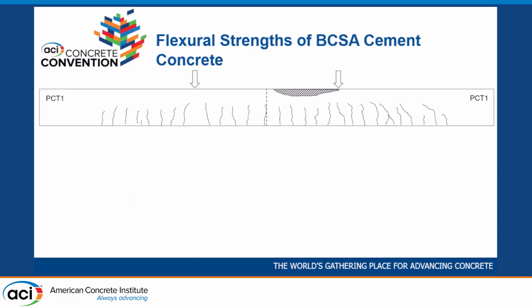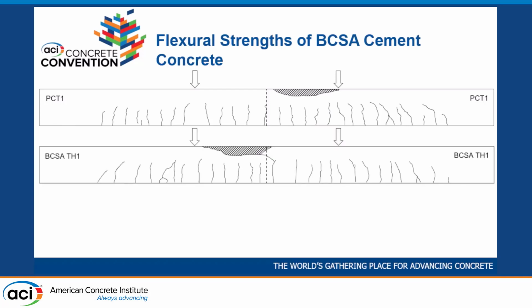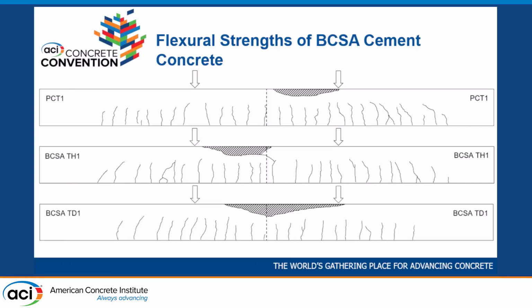So the first thing we looked at when we tested these beams was just qualitatively, what does the cracking pattern look like? Are we seeing things that look like flexural failures? So this is one of our Portland cement tension-controlled beams. This is a BCSA beam that we tested as soon as we could get it out of the forms and put into the load frame. So about 4 to 5 hours after casting. And you can see very similar behavior, distributed flexural cracking. The cracks are about the same height, similar number of cracks. That's all good in terms of the flexural performance. And this was true when we tested our BCSA beams at 1 day of age as well. So, the performance is just as good after they start gaining strength.